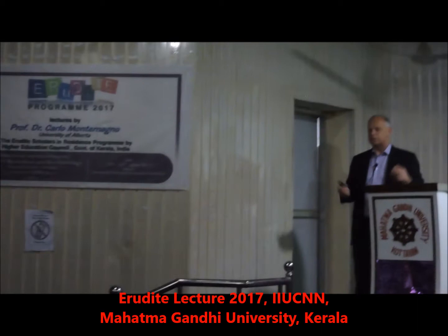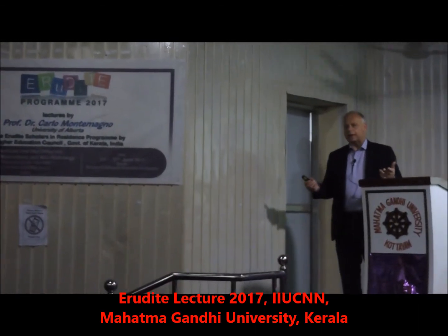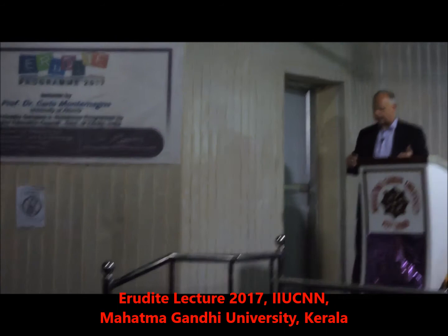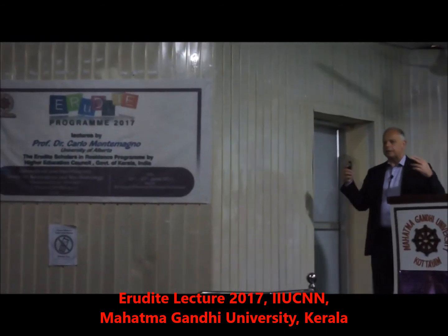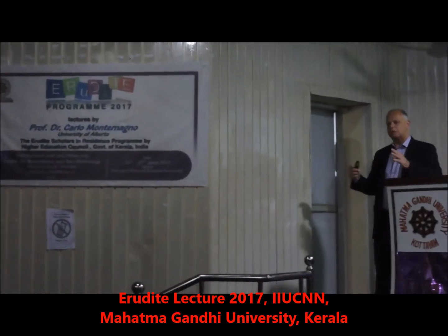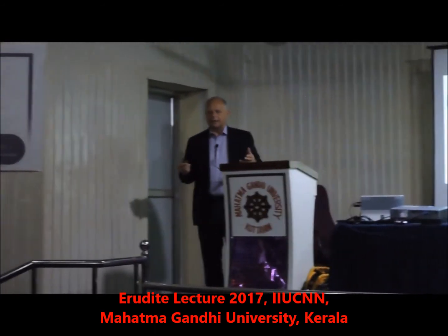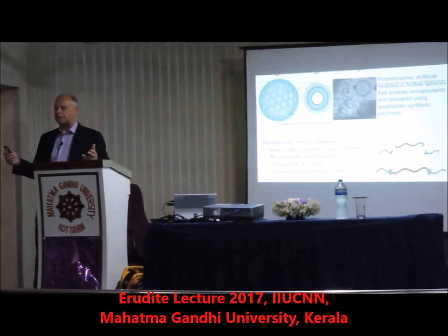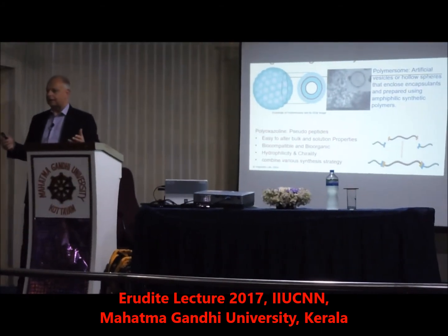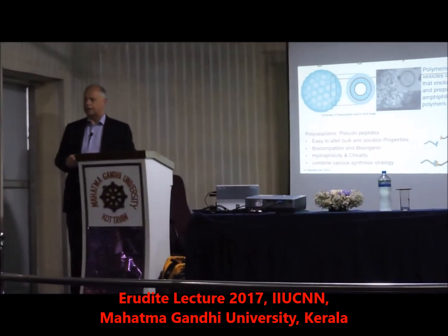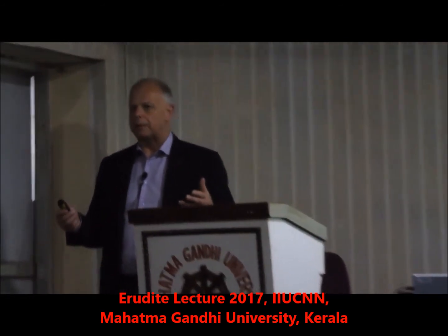And for the last 15 years, I've been working on trying to solve these problems. And one of the first things that we did was we needed to make a stable system for assembly. So we developed a block copolymer structure that has the same principal structure that you would find in a membrane in a living system, except if you cross-link it, it has the physical properties of plexiglass, and it withstands pressures of 10,000 psi, and it allows these molecules to keep on functioning well beyond 60 degrees Celsius.